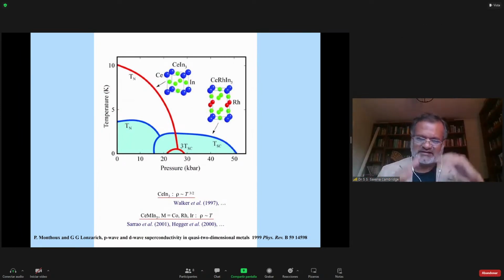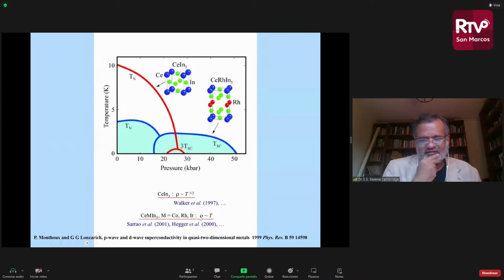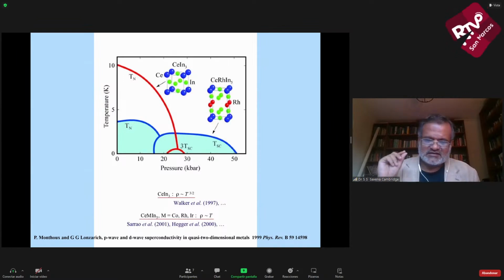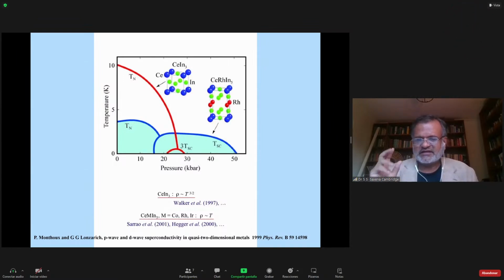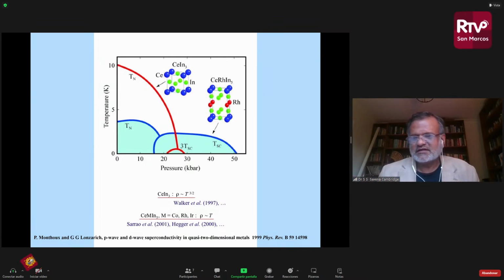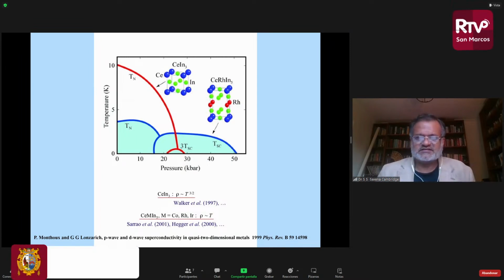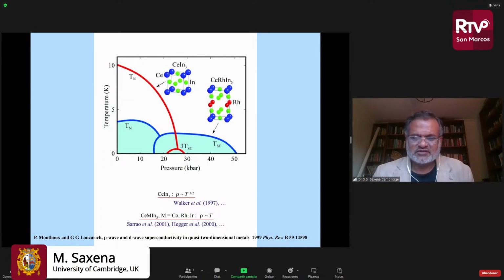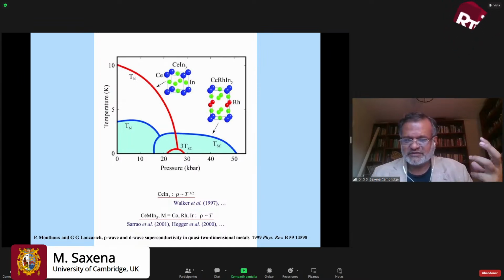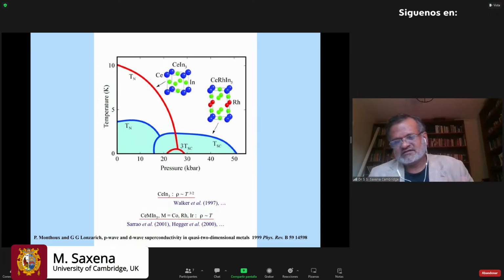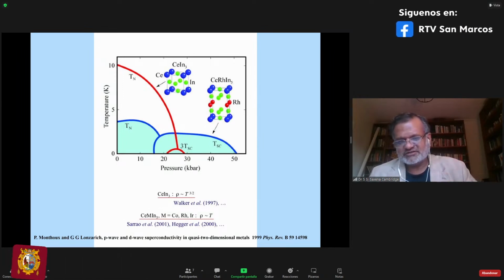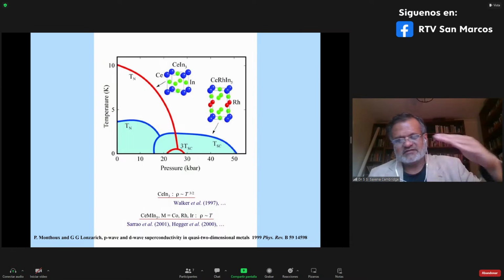And this was found in these kind of materials on a wide scale. Several other examples were found. For example, here, this is a whole series of cerium, cobalt, rhodium, indium. But given that it's a metallic system and it's an F electron system, and energy scales are such that superconductivity happens at fundamentally low temperatures, tunability in some sense is much more viable, because with these F electron systems you get more for your pressure when you squeeze them. But on the other side, things happen at much lower temperatures, even though we can enhance them quite a bit within those low temperature scales.